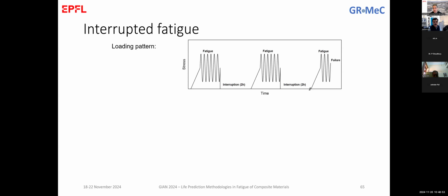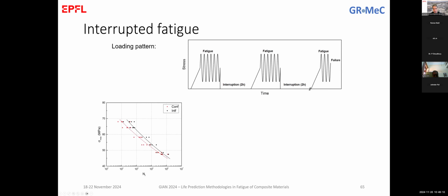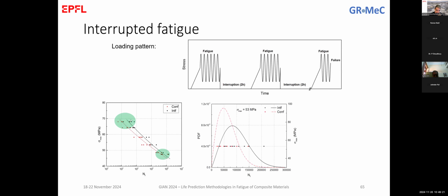So we'll continue with this interrupted fatigue loading to see how the behavior of the material is when we interrupt the continuous fatigue and we unload completely. So in this case, again, we did similar testing and we created two SN curves. In these SN curves, we can see that there is an obvious improvement of life. The interrupted loading, the black curve here, shows a significant improvement of life that is also more obvious at the high stress levels than at the lower stress levels.